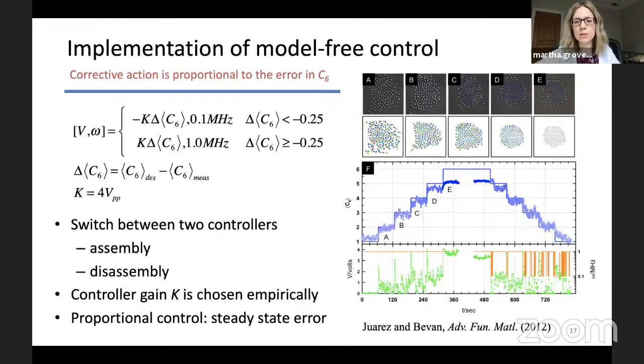There was a paper published, again by my collaborator Michael Bevan, in 2012 with a proportional controller applied to the system to try to drive it from a melted state to the ordered crystalline state. But what they found was that this controller wasn't really that satisfactory. It didn't always take. They had steady state error sometimes, and it wasn't able to deal with anything more than condensation and pushing on the system, not subtleties like defects in the crystalline lattice.